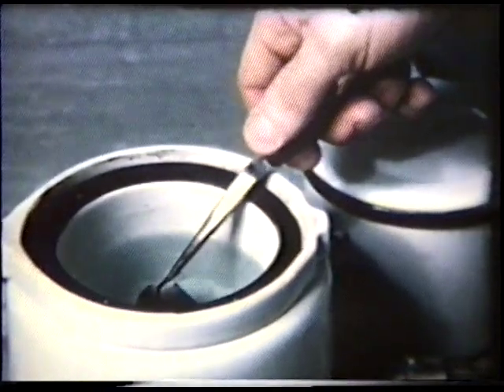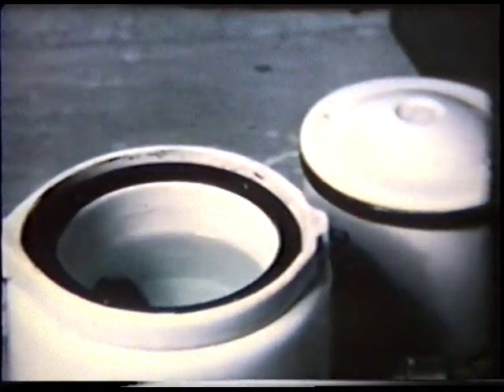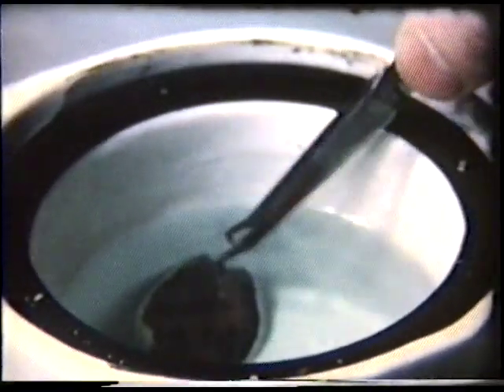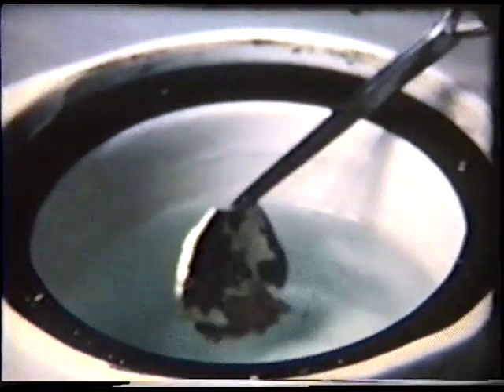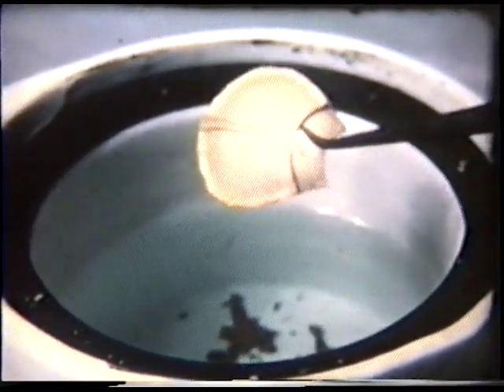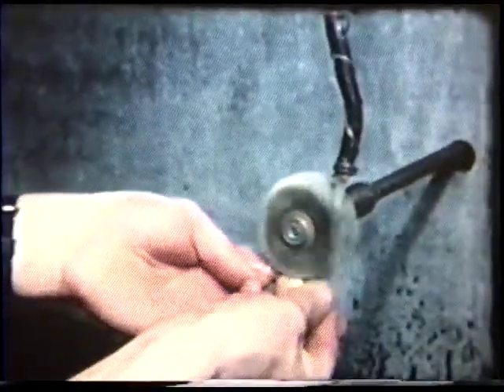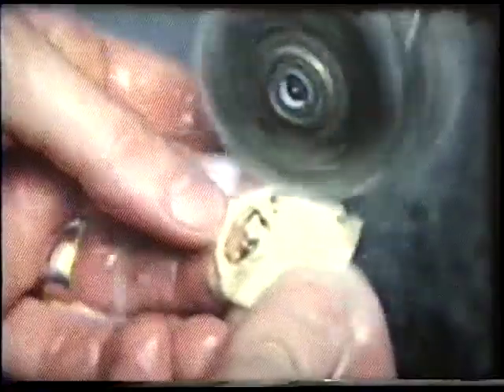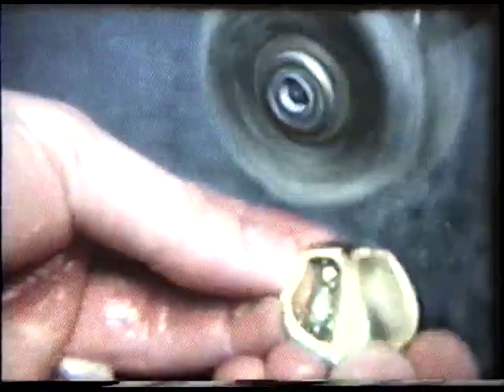A hot dilute solution of nitric acid removes the black oxidation formed during the cooling of the piece and causes the coating of yellow ochre which protected the undersurface to flake off. The back is burnished to restore the luster by brushing it with a brass brush revolving in a stream of soapy water.